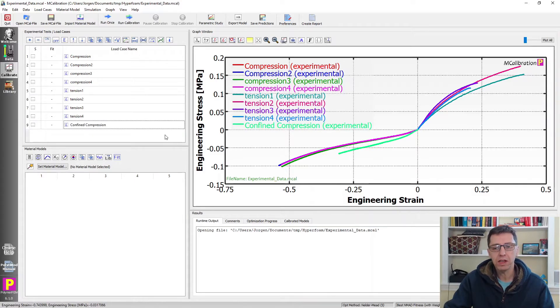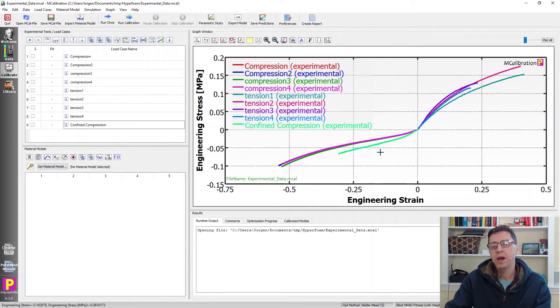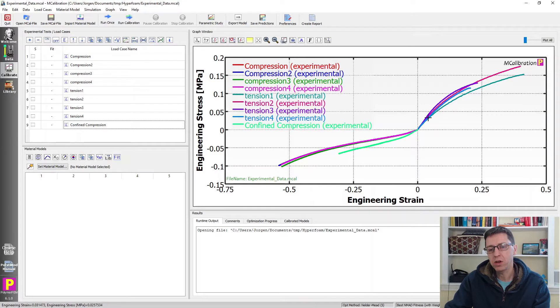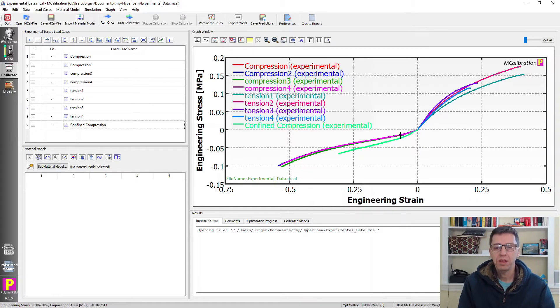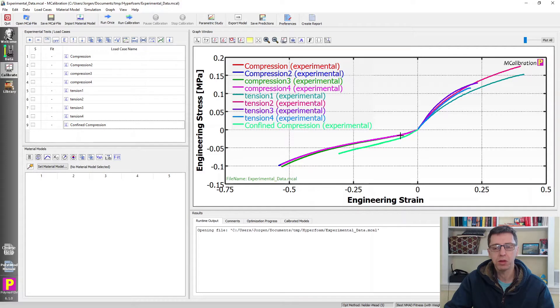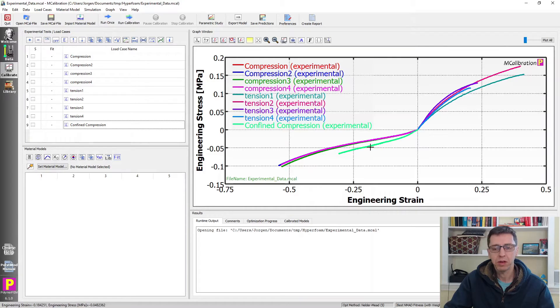So this is the data that we got on this foam. The first thing we look at when we see this data is this looks kind of weird or interesting. We see particularly that the slope here in tension, Young's modulus is smallest in tension, is not exactly the same as in compression. There's a little bit of an asymmetry there. And if you think through this, you will realize that any of these foam models that I just talked about, none of them can do that. That's not a capability that comes with those models. So that may cause us a little bit of trouble.